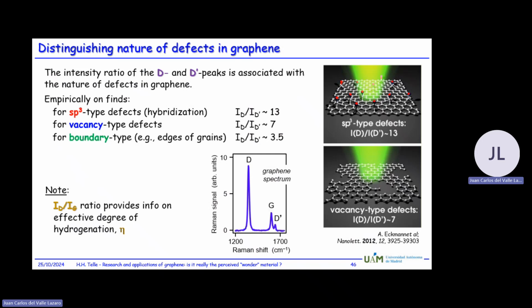So again, you here exploit that there are different transitions in the bands of graphene. And if you look at the ratio between another peak, not the G peak we had for determining how much hydrogen or tritium is on the surface, or any other atom if you want, that gives you some idea about the amount of adsorbed particles. And the ratio between these two other peaks gives you information about how much damage is in your system. So if you do that, you can actually quite nicely distinguish between different types of disruption of your current in your system, whether it is sp3 types, meaning you have adsorption of atoms, whether it's vacancy types, where you have actually damage to the graphene layer, and so-called boundary types, where you actually are at the edges of your system.